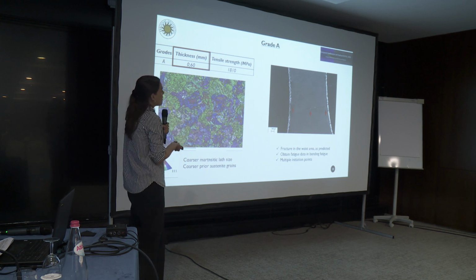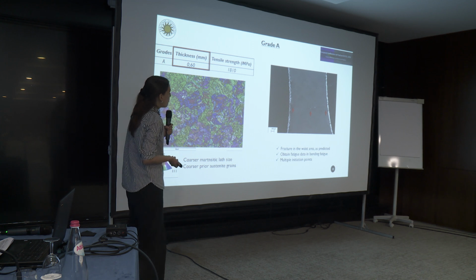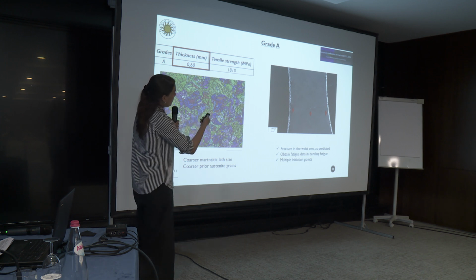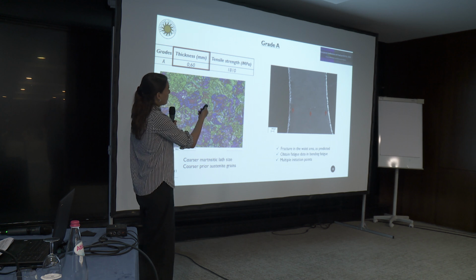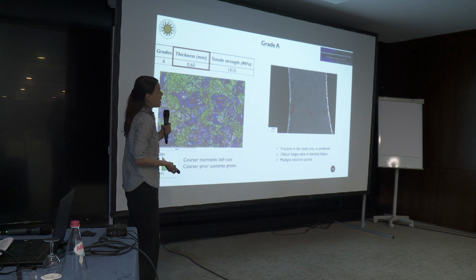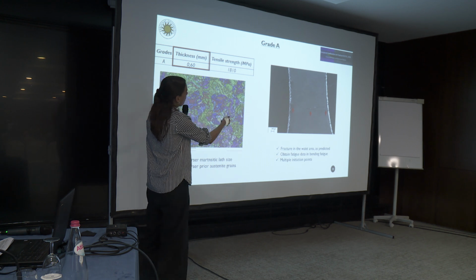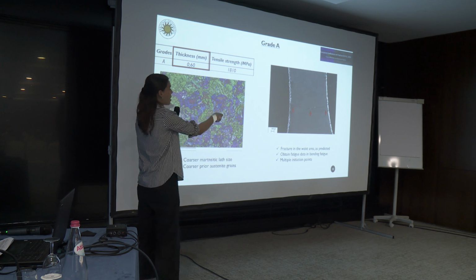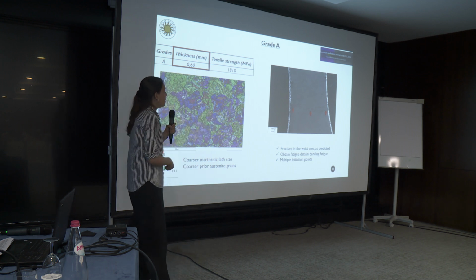You can see a fracture surface of this grade in the SEM photo. Here it is very clear how the EDM edge surface looks, and how the crack initiation points are at the edges. But also we have one in the middle.